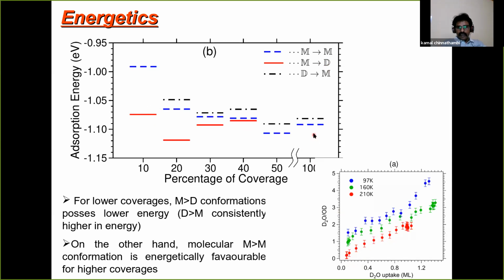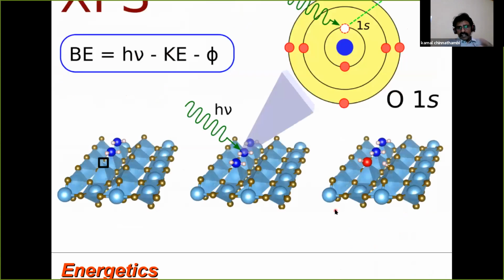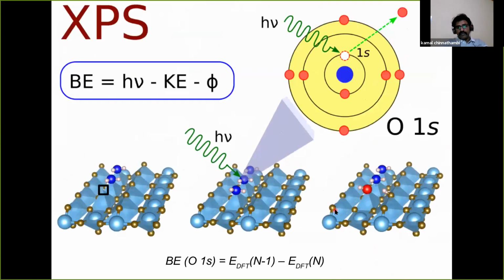When you go to the higher coverages, we see that linear chains are formed. In that case, only the molecular species is favorable in energy. That is also consistent, because when you go to higher coverages, the ratios keep on increasing, meaning that the degree of dissociation keeps on reducing. So this is energetically the trend, consistent with the ratio. Then again, as a reminder of how we do the calculation, I'm calculating the difference in energy between the N and the N minus 1 electron system, where one electron has been removed from the oxygen 1s.